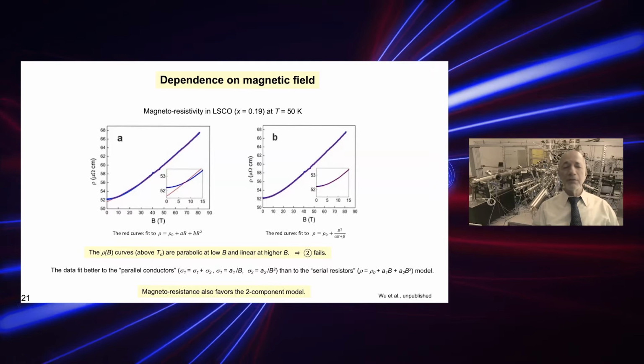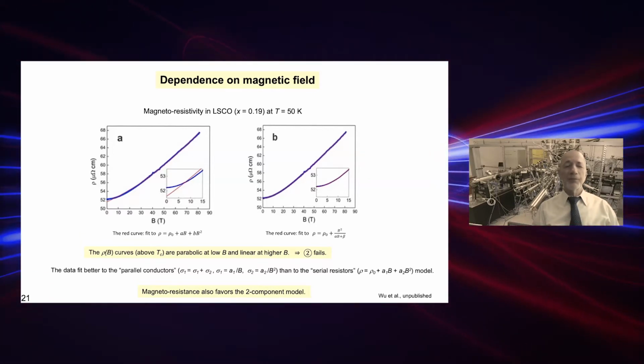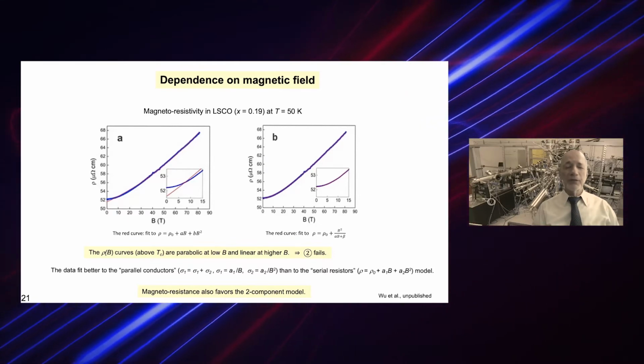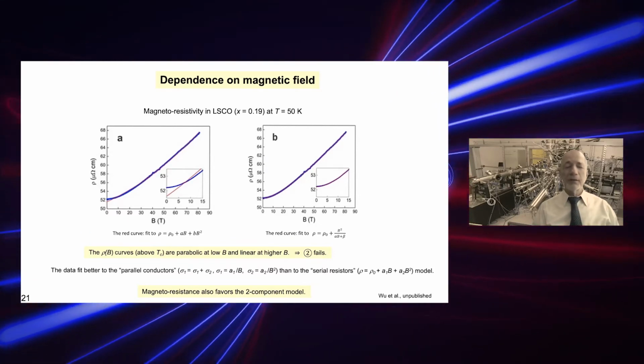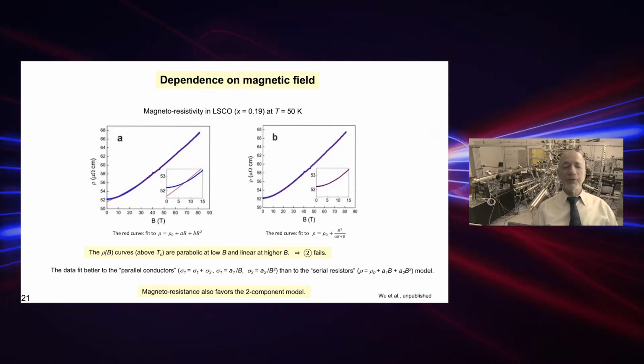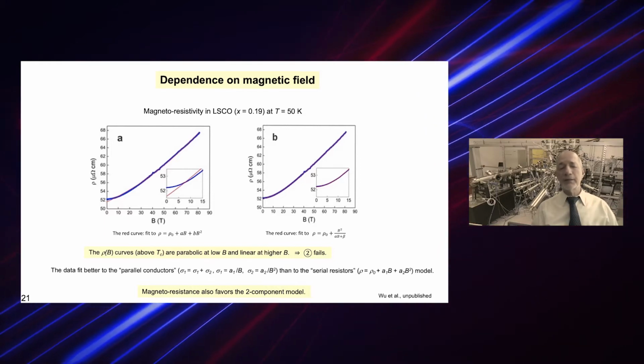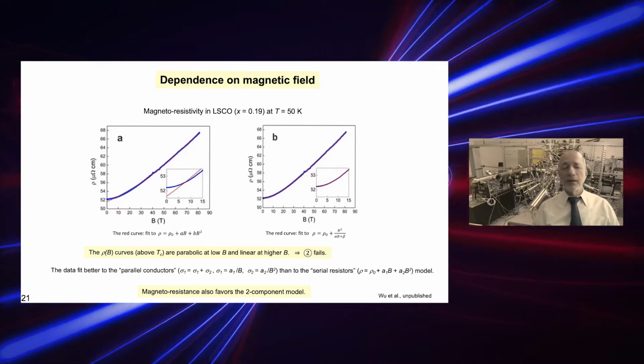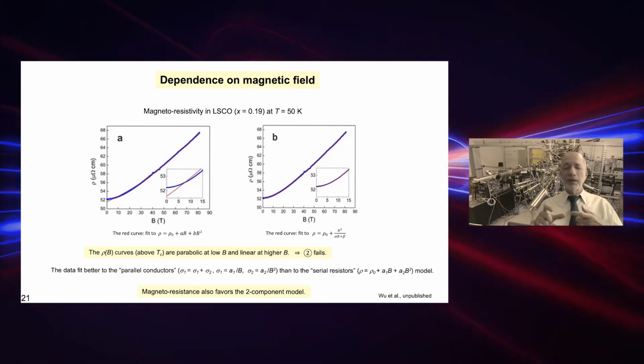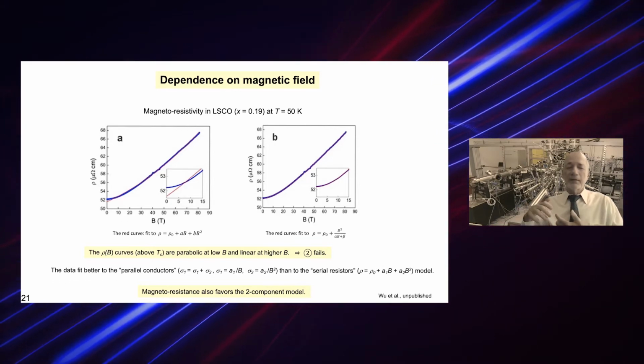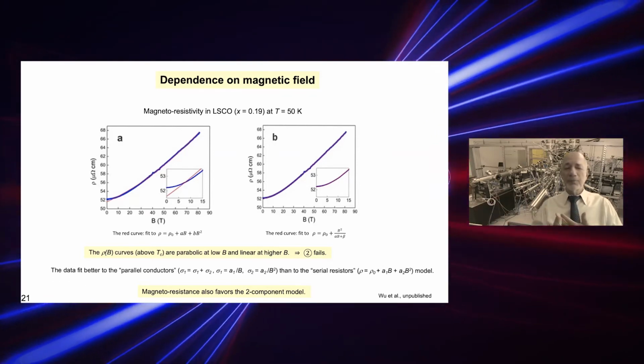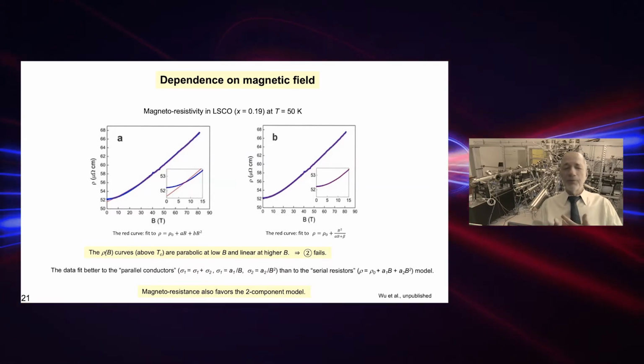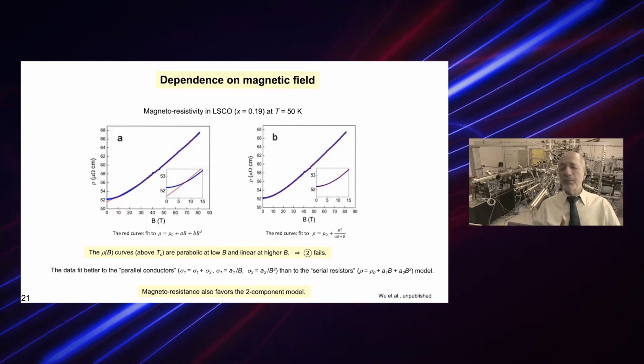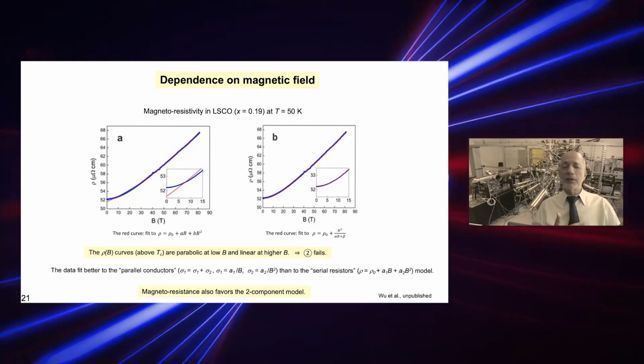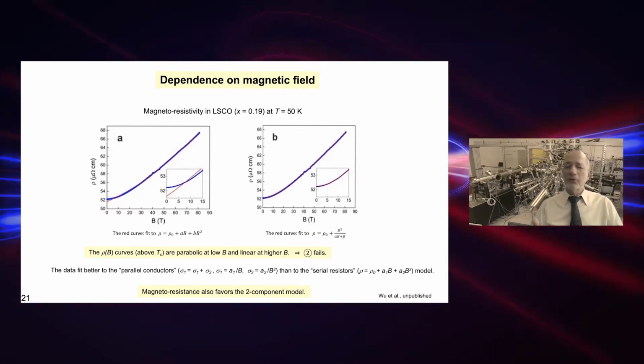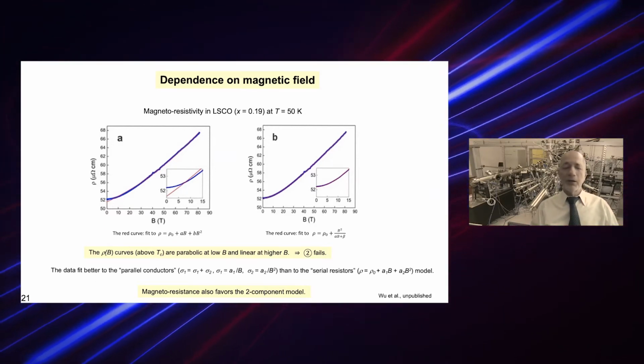But my point is that if you look carefully, this fit to the series model is actually not very good at low fields. And that should be obvious from the shape of the curve. It is parabolic at low fields and linear at high fields. And that's not what you get if you have x and x squared in series. At high x, x squared has to win. So you would expect linear behavior at low field and parabolic at high field. What we see is the opposite, and that points to a parallel connection, in which case the higher conductivity wins. And to the right is the fit to the parallel conductivity models.